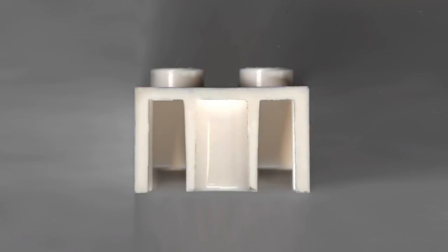And what's most clever to me is where Lego designs their draft angle. The outside of a Lego brick must be square. So if you cut a Lego brick in half, you can see that these inner supports are thicker at the top than at the bottom. There's a draft angle of about one and a half degrees. This helps the ejector pins push the brick off the mold.